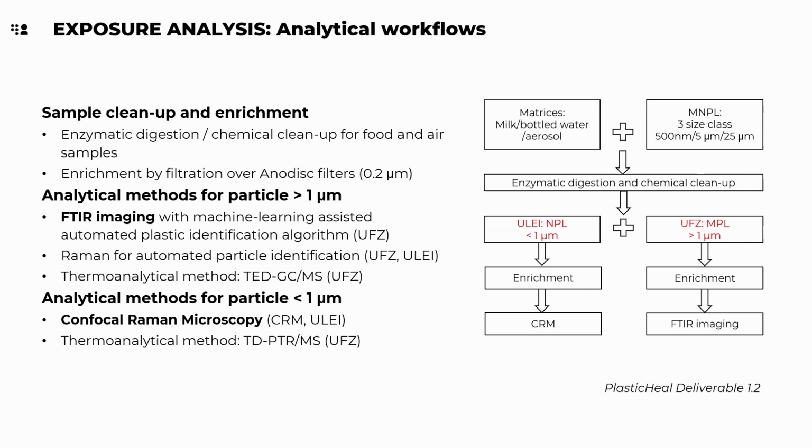So I'm going to give you some examples of the development and application of these models. For instance, for the exposure analysis, we have worked with the analytical workflow that you see on the slides. We have basically collected the sample, did a cleanup and enrichment, then we filtered all these materials, and then we assessed the micronanoplastics in the filter by means of the two techniques that distinguish nano on one side and micro on the other side.